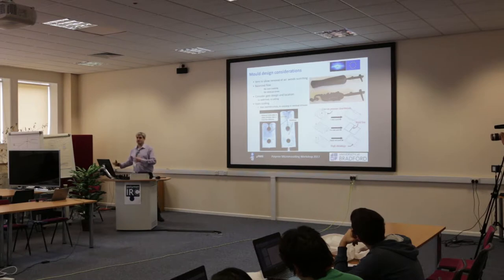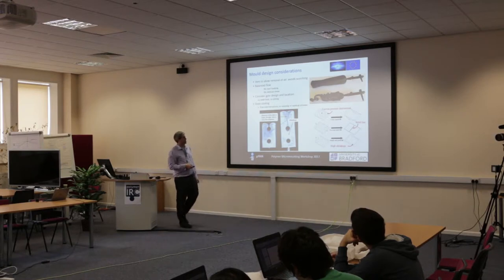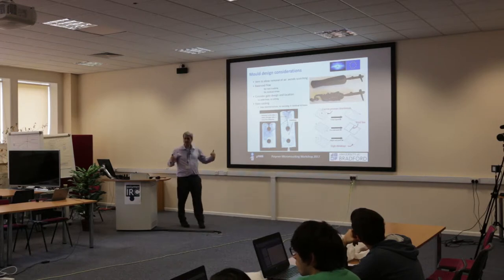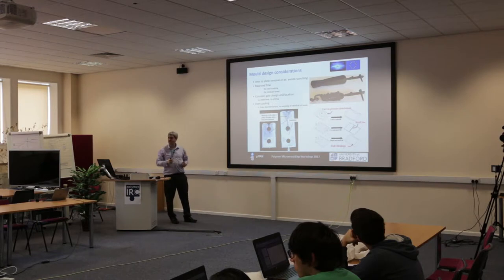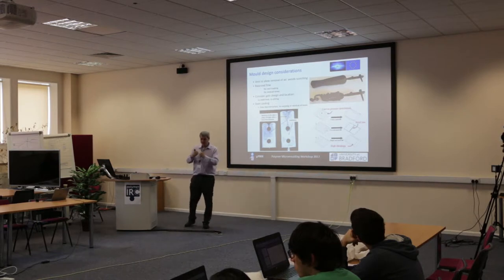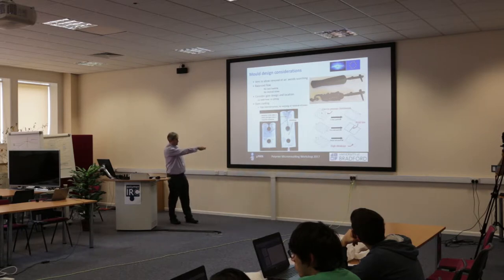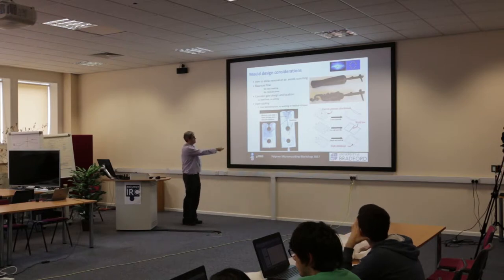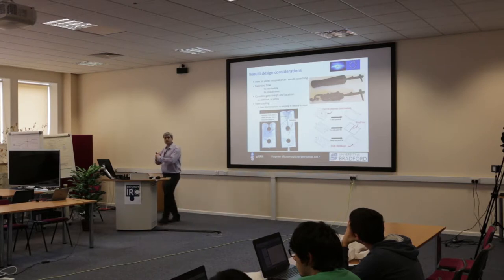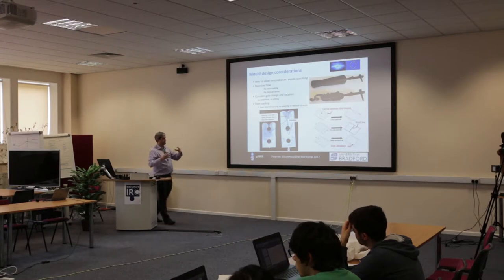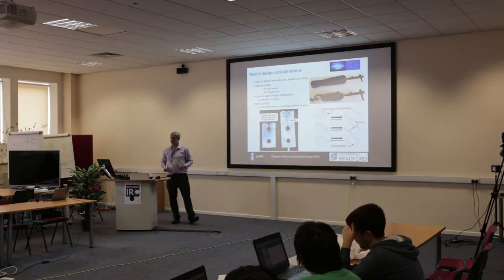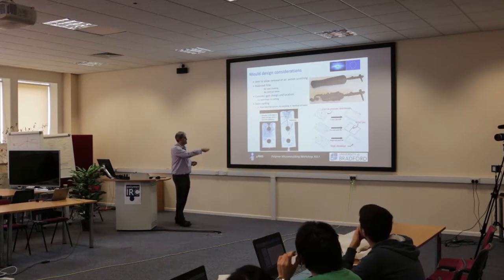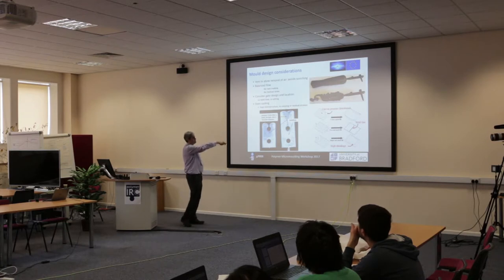Gate location can be quite challenging because we want a nice uniform pressure distribution throughout the part while avoiding key problems like weld lines. Wherever two flow fronts come together, we get weld lines — the coldest material at the flow front doesn't knit well when it impinges on itself. Flowing around bosses to create holes always produces these weld lines, which are clearly visible on many components and are a source of weakness: molecular chains in that region don't fully diffuse with each other, creating a boundary that can cause stress concentrations and guide fractures.